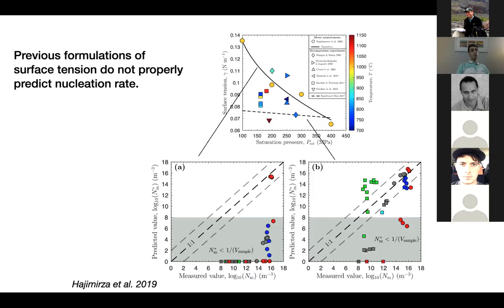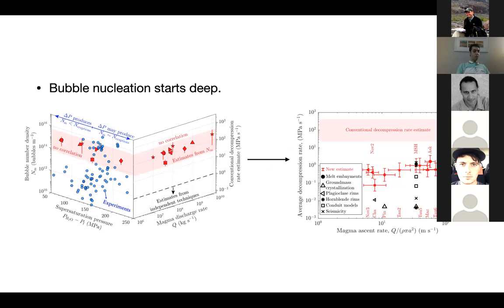This is a great improvement over previous formulations for surface tension, shown here. The comparison of bubble number density in model and experiments are shown here based on these experiments. So in the next step, now that we can simulate nucleation in experiments, we coupled our nucleation model with a conduit flow within a cylindrical conduit to infer nucleation kinetics from observed vesicle textures. First, I'm going to focus on bubble number density.